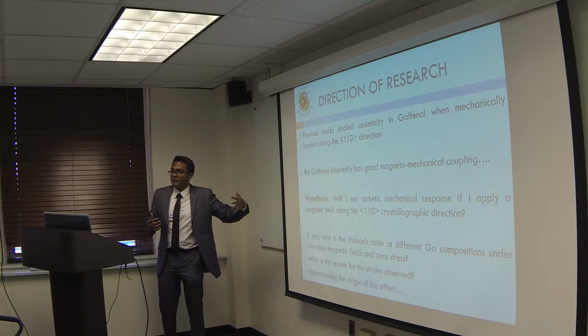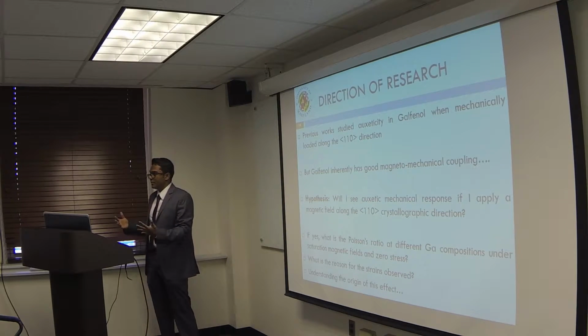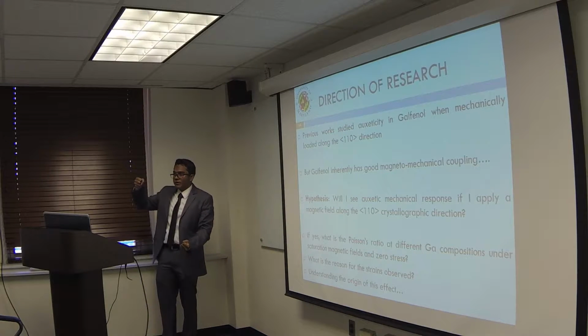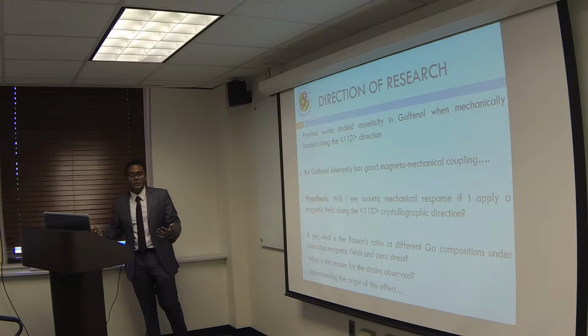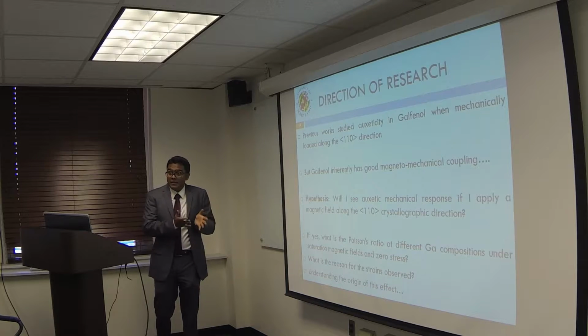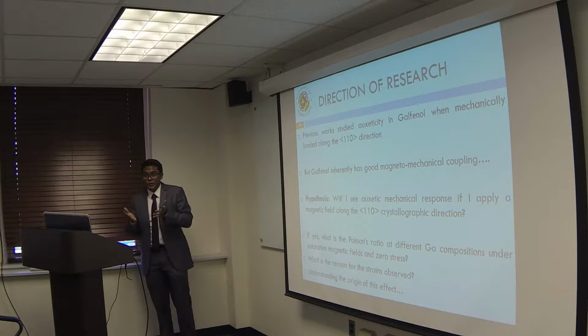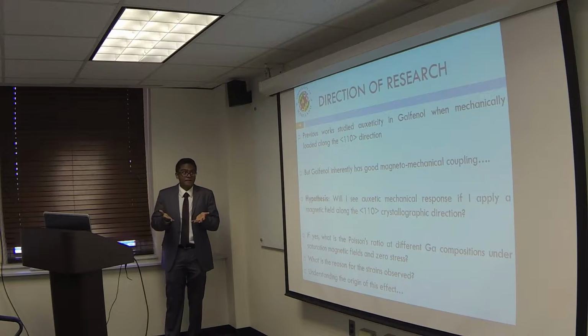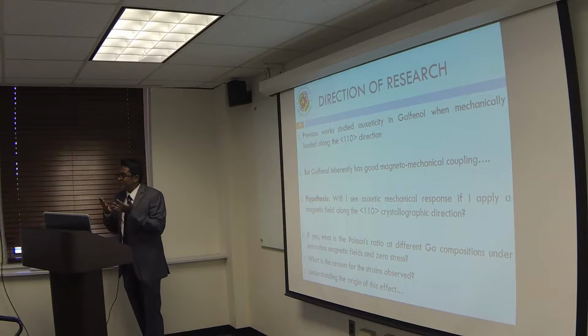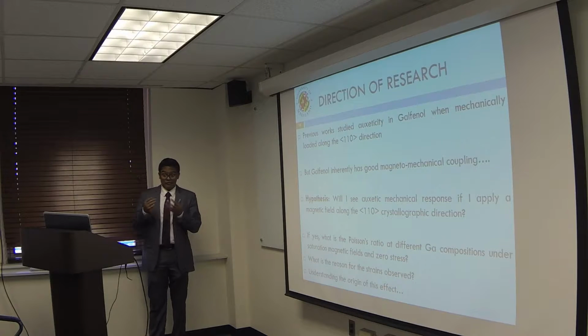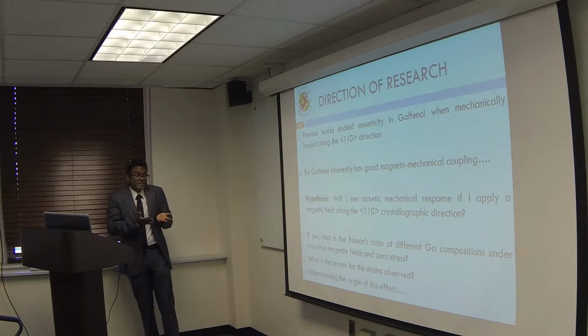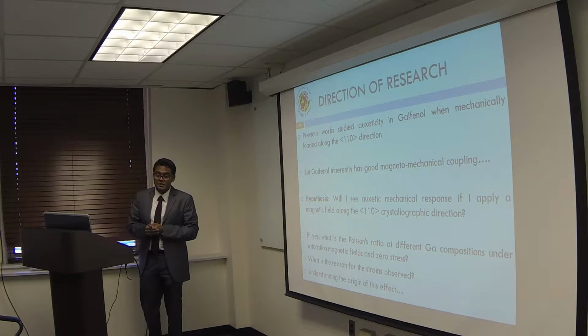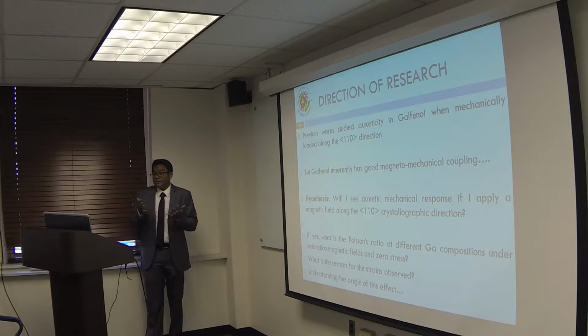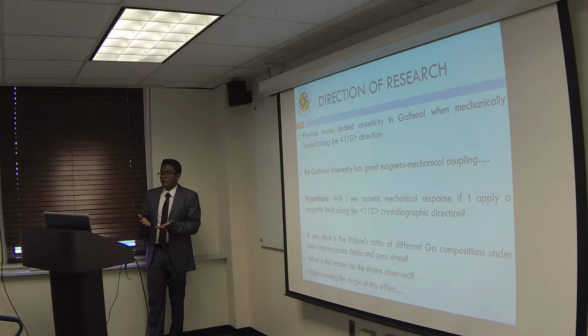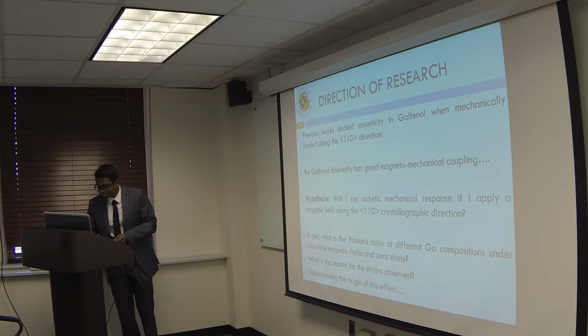So up until now, everybody has looked at Galfenol as yet another material which, when you pull along a particular direction, you get a negative Poisson's ratio. But Galfenol has inherently good magnetoelastic coupling. So the questions that we were interested in were: will I be able to see the same effect if I apply a magnetic field instead of tensile stresses? And if I do see this effect, how does it vary at different gallium compositions? And what is the reason for the strains observed, and what is the origin of this effect itself in Galfenol?